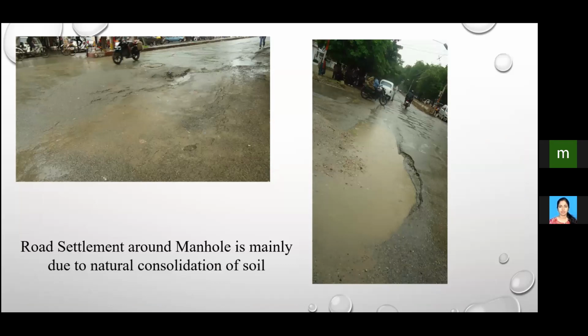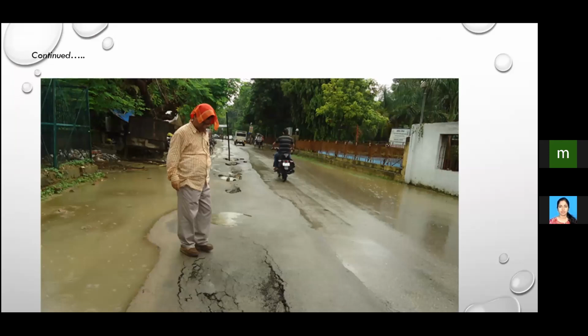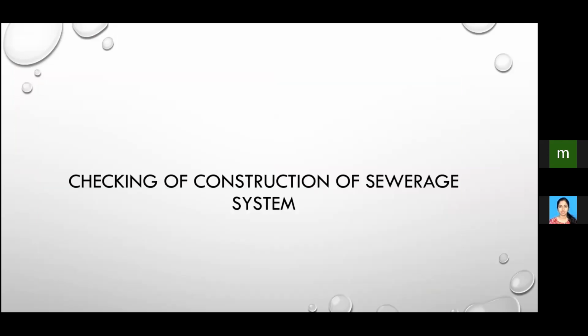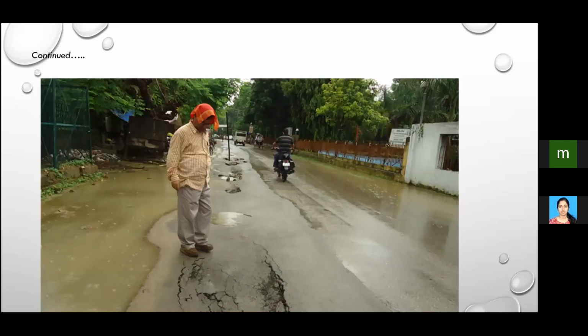Now here, you see the road settlement around the manhole is mainly due to the natural consolidation of soil. While constructing manholes, in fact, there were some manholes which were wrongly constructed or not constructed in a proper way, and that led to the breakage of roads or the settlement of the road, as you see here. In a lot of places, particularly during this monsoon period, the road got settled, manhole broken. You can see this road settlement near the manhole. Then we checked these physically, and we took the samples and got them tested in the nearest laboratories, NIT Allahabad, sometimes our place, sometimes IIT Kanpur, or some reputed organizations also.